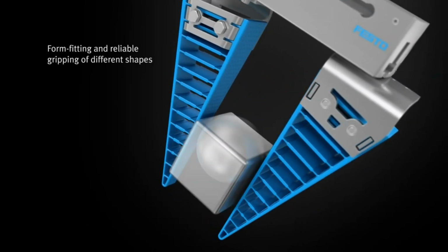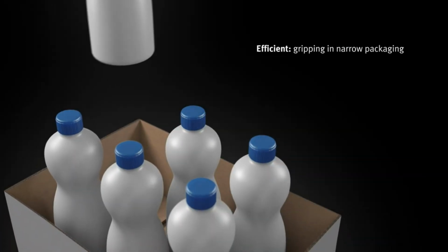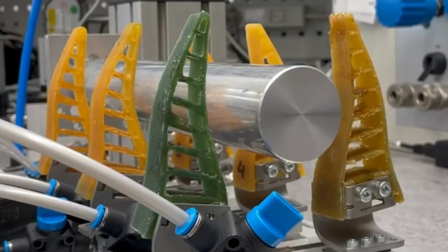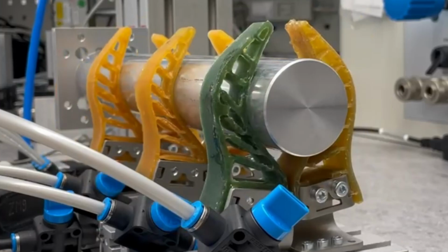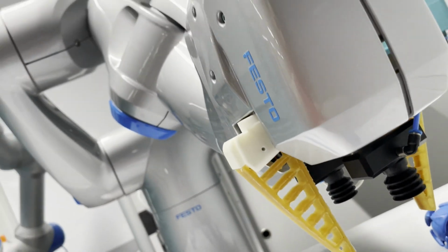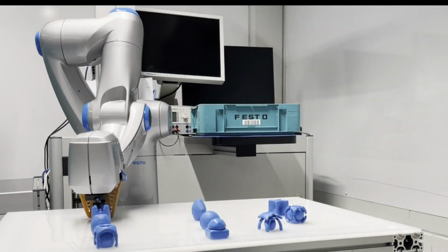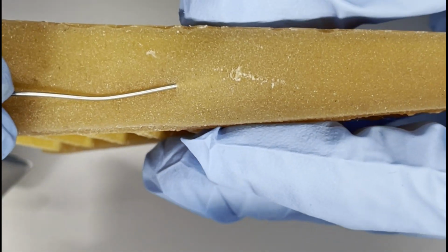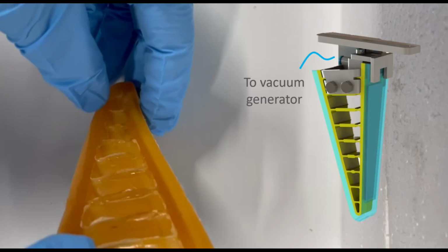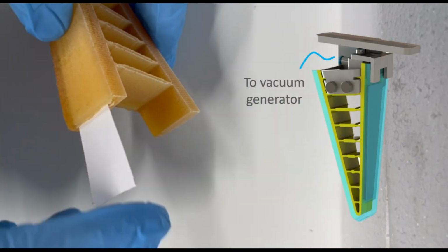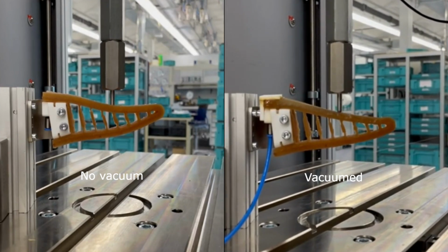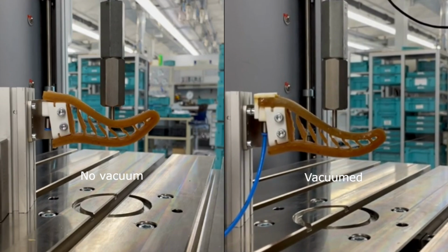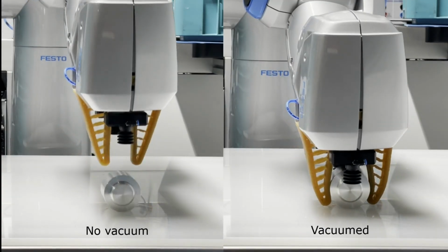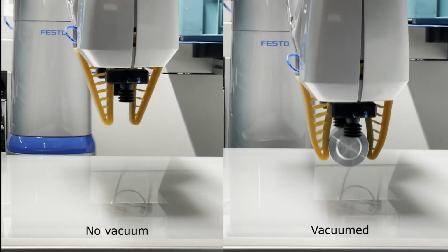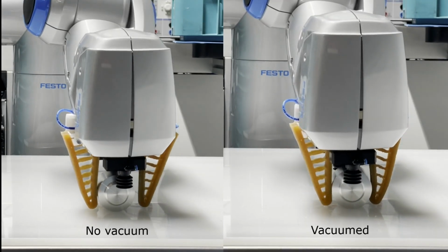In my collaboration with Festo, a leading automation company, I integrated the self-healing technology into one of their commercial gripping tools. I developed the Festo finger from self-healing materials, and to accelerate its return to operation after healing, I introduced a variable stiffness scheme. This variable stiffness scheme consisted of a self-healing chamber attached to the main finger. Inside the chamber, I placed thin layers of sandpaper. When vacuum was applied, these layers compressed together, significantly increasing stiffness. This allowed the gripper to actively compensate for the softening effect caused by heating during healing, restoring its ability to apply the same force as before damage.